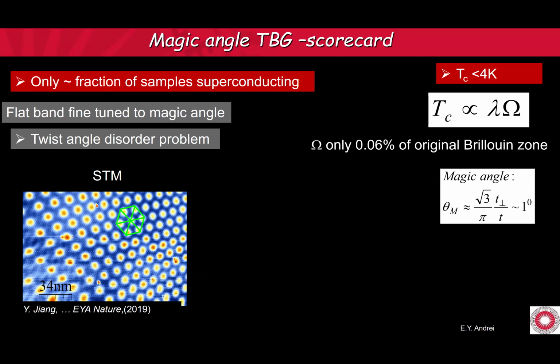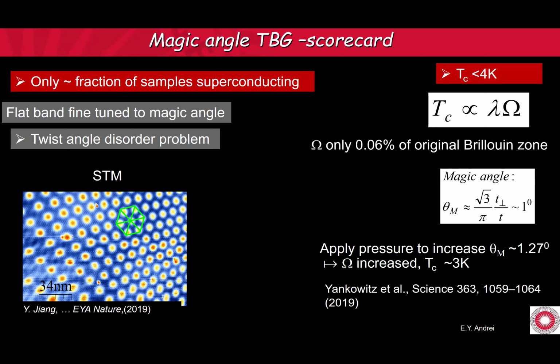So one trick to get there is to actually apply pressure. And this was done by this group here at Columbia, but they applied a huge amount of pressure, and they were only able to change it from 1° to 1.27°. Tc increased a little bit, but this is not the way to do it. One has to figure out another way. Huge amount of pressure means different things to different people. 3 gigapascal? Oh, low pressure.